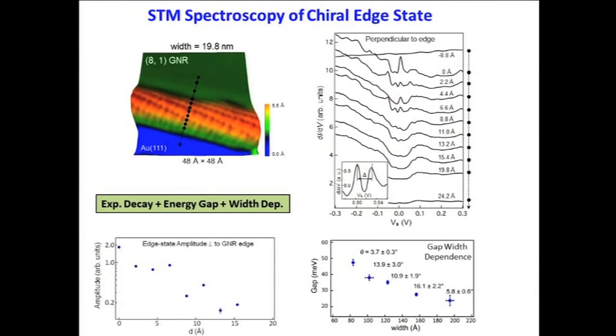And here I show the data. This is a plot of dI/dV versus voltage. The first point, I can barely see it, but there's a black dot there on the gold. That refers to this top curve. So on the gold, you see the spectrum is featureless. But here, as we go into the edge, I want you to focus on this low energy regime, which I refer to as the elastic regime. And what we see are these peaks suddenly sprouting up here at low energy.